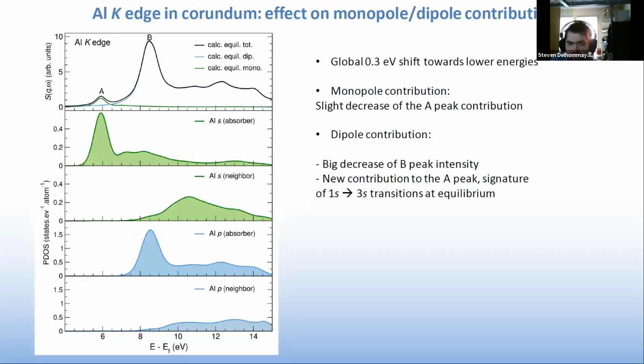So here, this is what I display: the calculation of projected density of states. Here we just have the K edge at equilibrium, so with the monopole and the dipole transition. And we can see that at equilibrium, the dipole does not show any contribution on the A peak. And then below that, you have the absorbing and neighbor aluminum S states and the absorbing and neighbor aluminum P